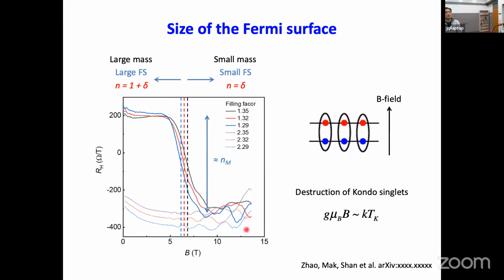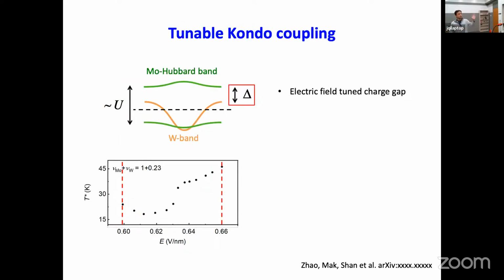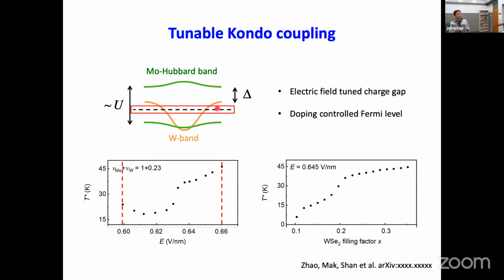So what's happening here with the magnetic field is that when the Zeeman energy from the magnetic field becomes comparable to the Kondo temperature, you forcefully break the Kondo singlets in the system, and then you decouple the free carriers from the local moments, and that's why the size of the Fermi surface suddenly drops from a 1 plus delta large Fermi surface to a delta small Fermi surface. Okay. All right, and we can also tune the electric field and tune the filling in the tungsten layer to continuously tune the Kondo temperature as well as the heavy fermion mass in the system. So that's a nice thing that one can do in this continuously tunable solid state system.